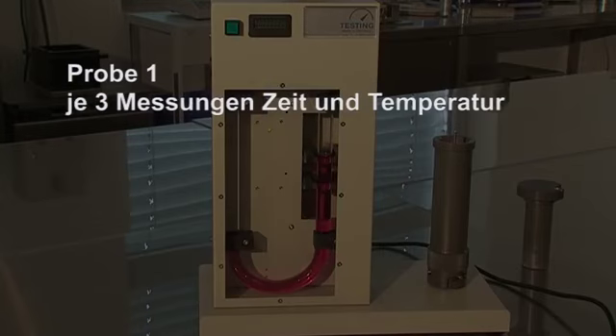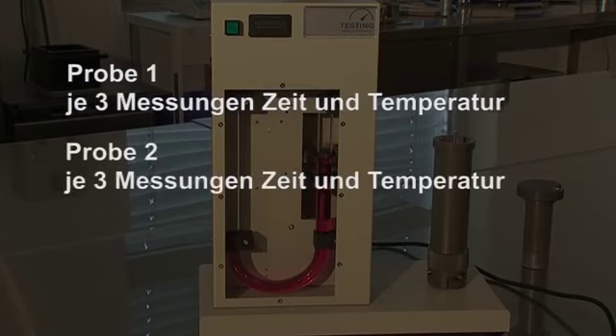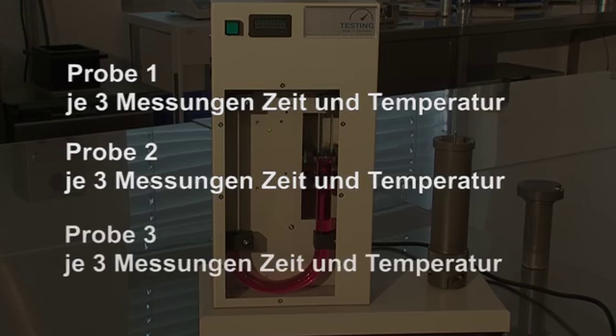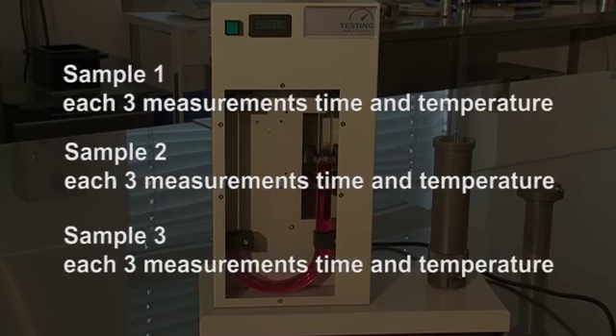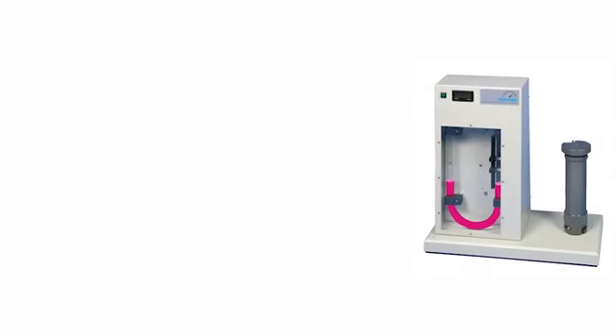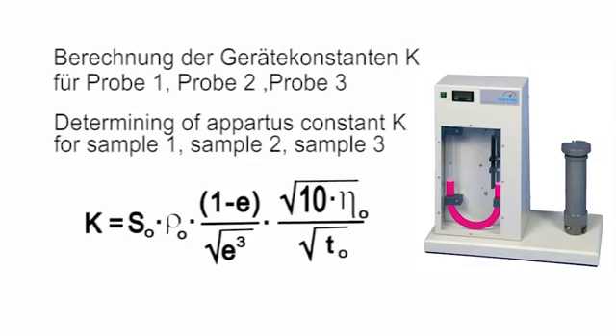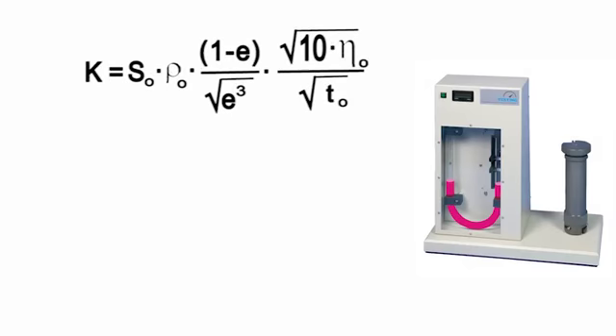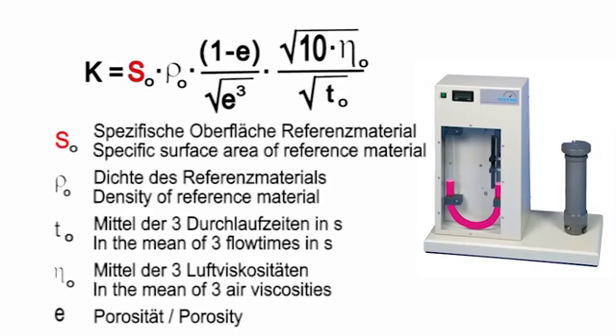Three measurements are carried out for the reference substance. The temperature must also be recorded. A second and third test are prepared with new material and carried out again for each three measurements and the mean value calculated for each test. The same applies to the temperature in degrees Celsius. The apparatus constant K is determined by each reference test to 2 places behind the decimal point from equation 3. In this, S0 equals the specific surface area, ρ0 equals density, T0 equals flow time, eta equals air viscosity, and E equals porosity.